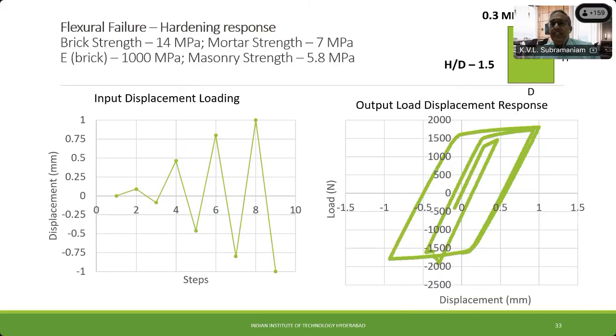Now, when we come to flexural failure, here is a wall which is slender, where the height is bigger than the width, and subjected to a moderate level of compression. What we get is a hardening plastic kind of response from this particular wall. So when it comes to cyclic behavior, we are able to handle and essentially see that the cyclic behavior of these masonry walls, depending on the level of compression and the aspect ratio, falls into one of three categories. It fails in shear, it fails in flexure, or it fails by sliding. And each one of them has a very typical cyclic response.